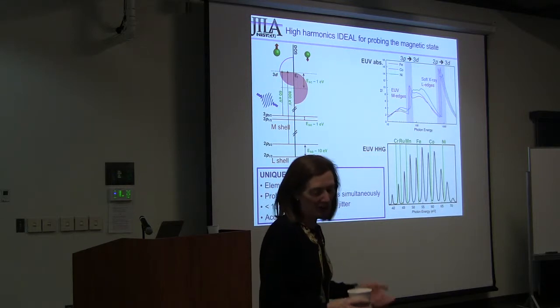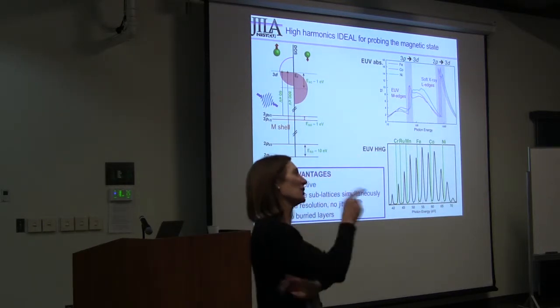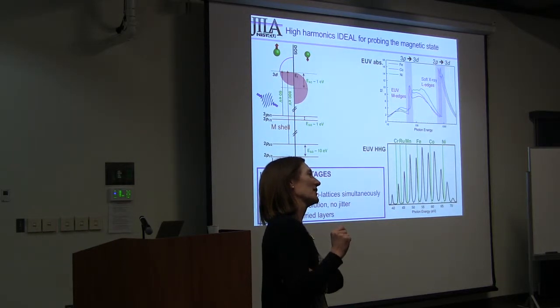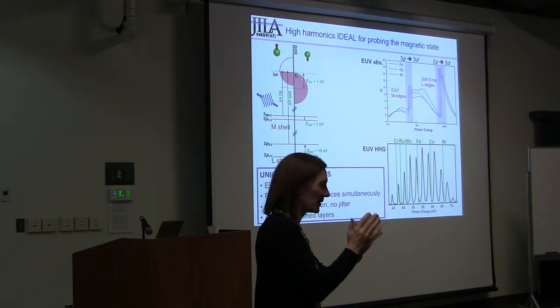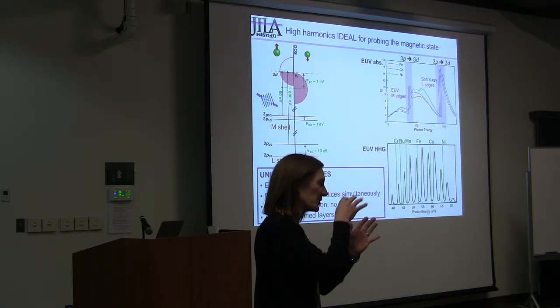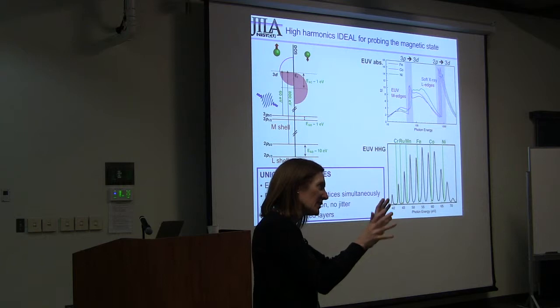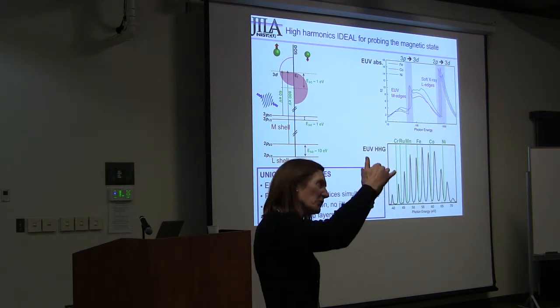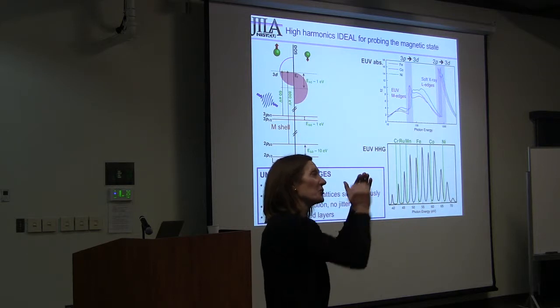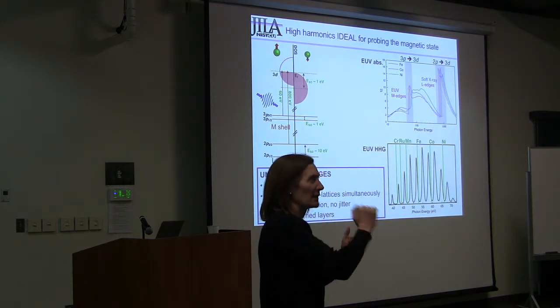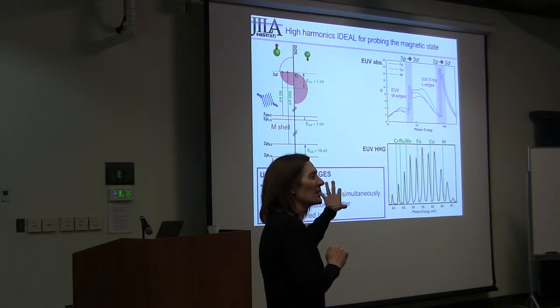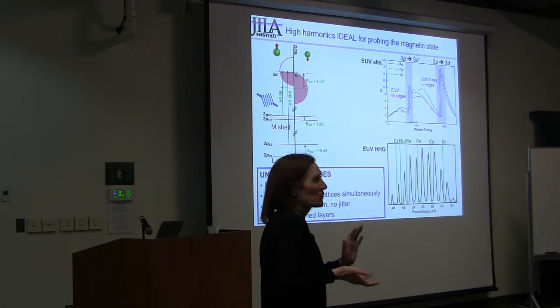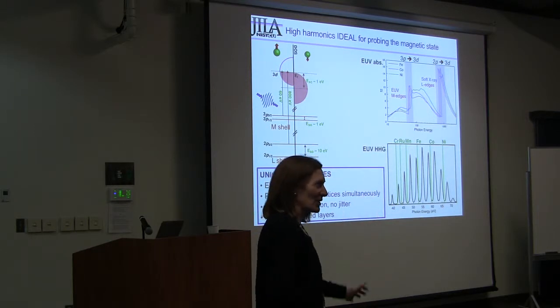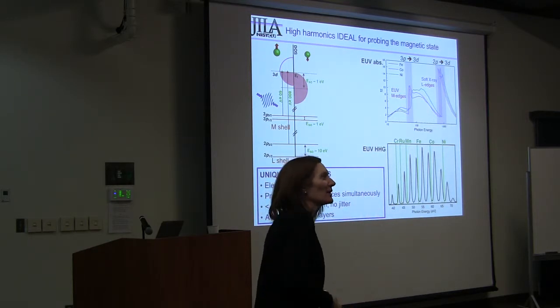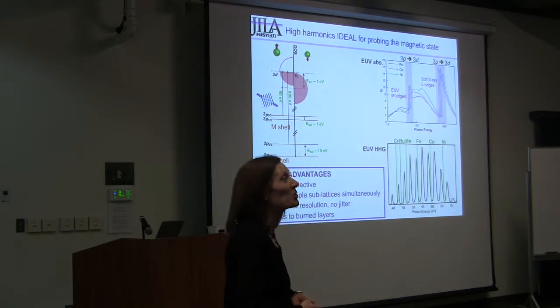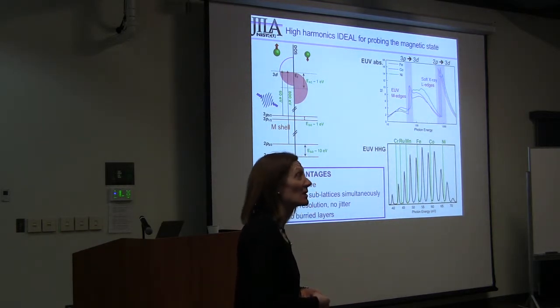So, okay, can I answer it in another few view graphs? And you'll see why I'm struggling. It has a concept that if you heat a magnetic material towards its Curie temperature, you're going to have relaxation, some randomization of the spins, so the magnetic moment will decrease. So statically, at any temperature, you can define the magnetic state. Is that right? The problem is in a dynamic situation, your spin temperature doesn't really mean a lot because everything is changing and interacting, and you've got scattering and transport and everything. And so spin temperature doesn't really have physical meaning, but you can use it to describe the level of magnetization in the material.